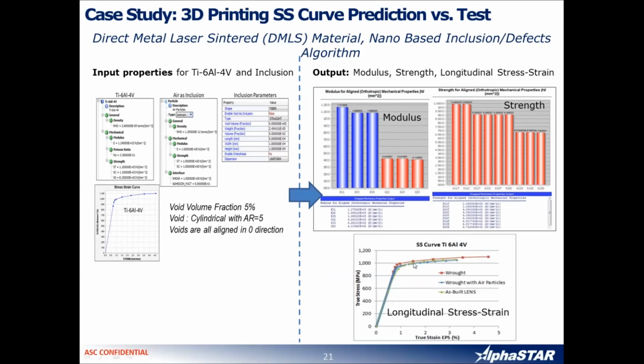test. For the wrought case, which is the red curve right here, for the wrought with air particles, and the given as-built LENS stress strain curve, it shows a pretty good comparison between the wrought with air particles and the as-built LENS. That shows that there were anomalies, which were inclusions as air particles, introduced inside the titanium aluminum to give us the correct stress strain curve, which can be easily compared with test.